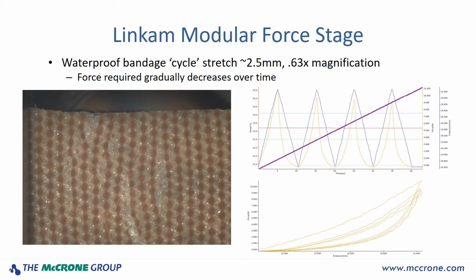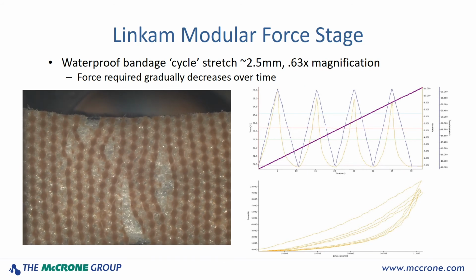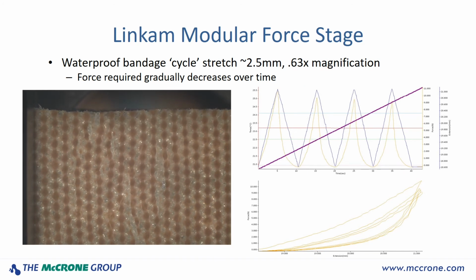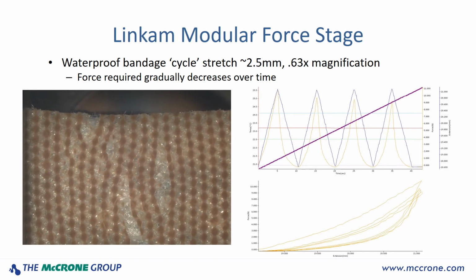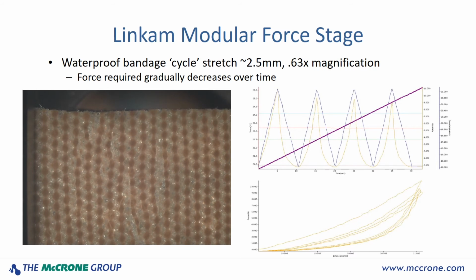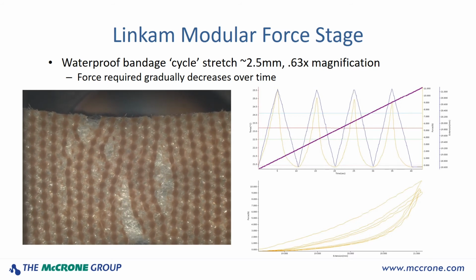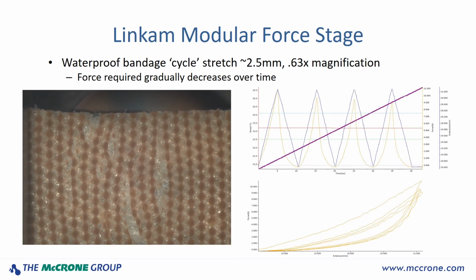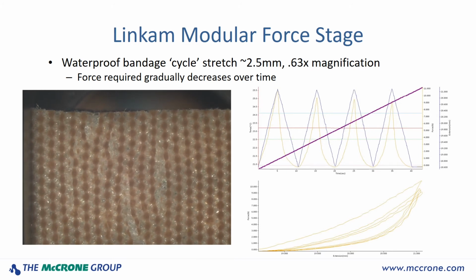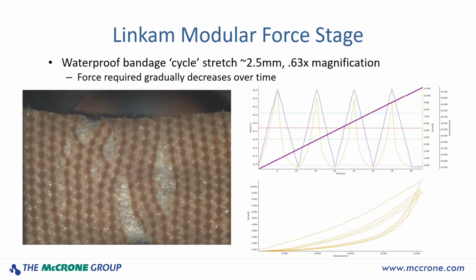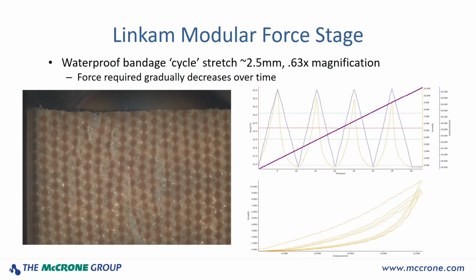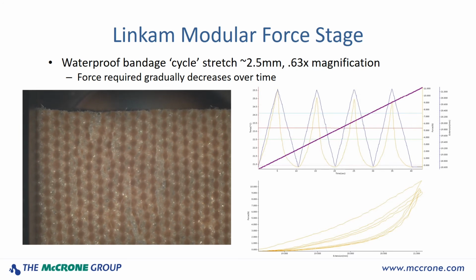The first test was for the waterproof bandage, utilizing a cycle stretch of roughly 2.5 millimeters at 0.63x magnification. What I noticed was that the brown dotted layer of the bandage tore apart quite easily after the first cycle. On the graph to the right, you can see the blue line indicating the extension amount over time, and the yellow force line below gradually decreasing at maximum extension as the cycles went on.